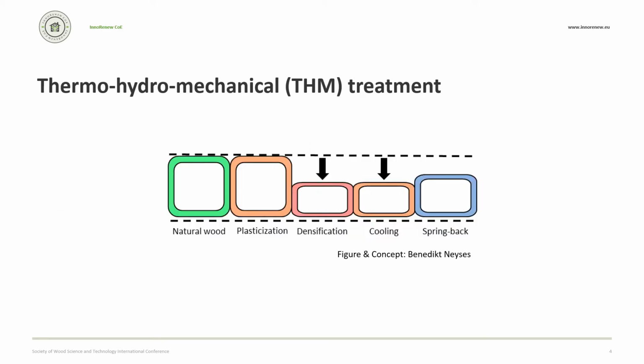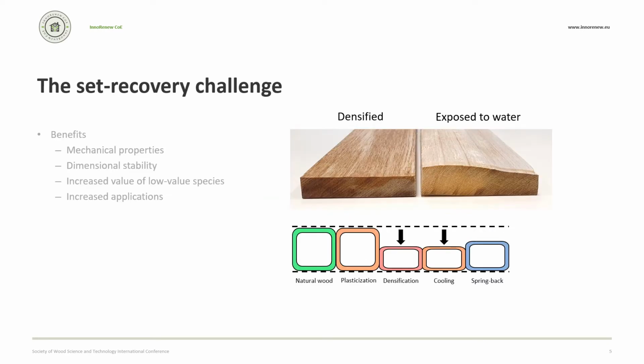The densification treatment takes place at the wood cell level and starts with natural wood cells being plasticized through heat and moisture. Compressive force is then applied to the wood and held while heating. The samples are then cooled under pressure and the load is released. As with wood panel products, a small amount of springback is observed. This process results in a densified wood product.